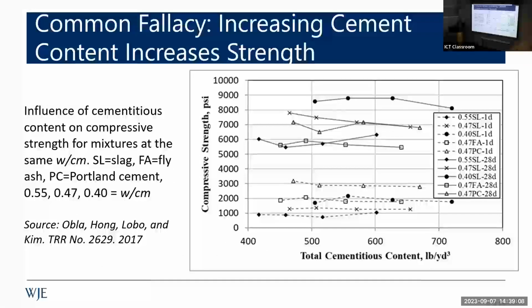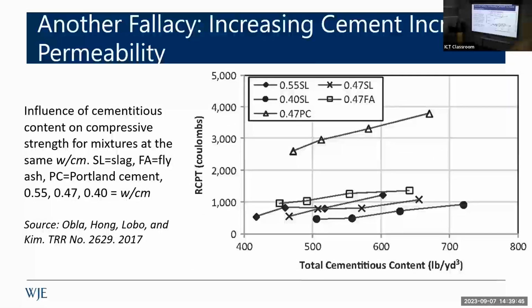A lot of people in the concrete industry, they'll swear more cement equals more strength. And it's actually a complete falsehood. This is data from NRMCA, National Ready Mix Concrete Association, showing 1 day and 28-day strengths for different mixes with different cement contents, holding water cement ratio constant. And what you see is you don't see any change really in effective strength. And then you say, wow, but permeability, we need more paste to be less permeable. And again, what you find is actually the opposite in some ways, that the more paste we put in, in some ways we get worse permeability.